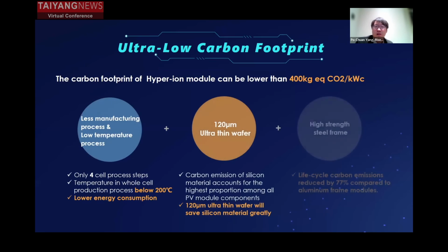So here I would like to explain why Hyper-ion product results in super low carbon footprint, which is 400 value. The first one is only 4 cell process steps, with temperature in whole cell process below 200 degrees Celsius, which means lower energy consumption during production. Next one is 120 micrometer thin wafer production. As you know, carbon emission of silicon material accounts for the highest proportion among all PV module components. Therefore, thin wafer will save silicon material greatly. The last one is high strength steel frame. Due to life cycle carbon emission calculation, it can reduce 77% compared to aluminum frame module. So in this case, we can get very low carbon footprint value.